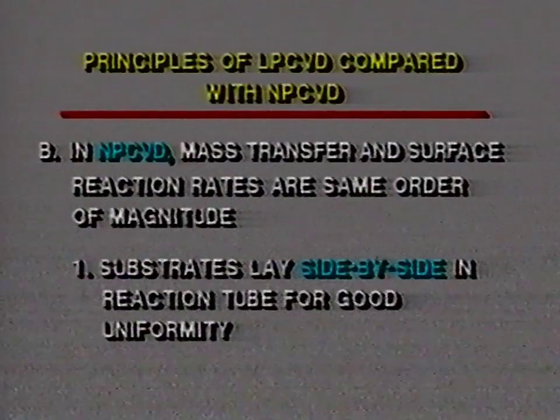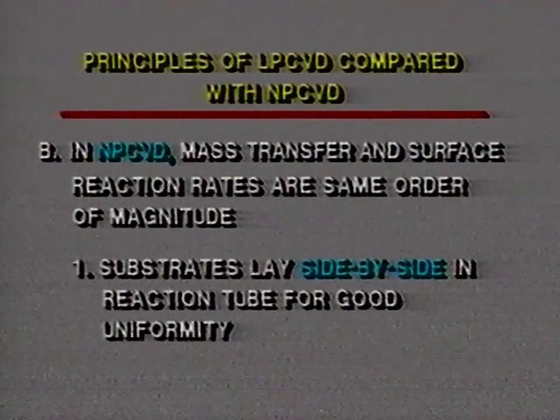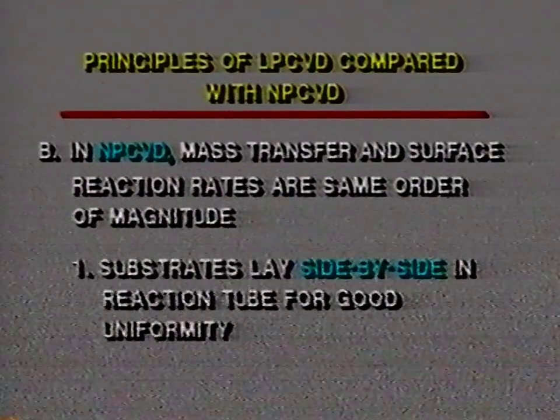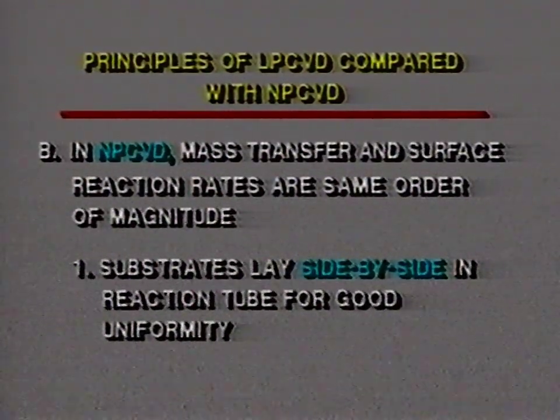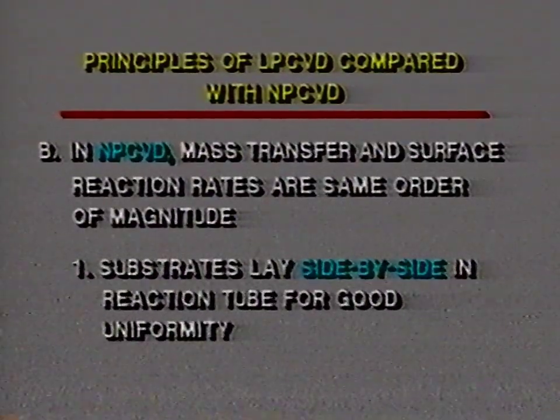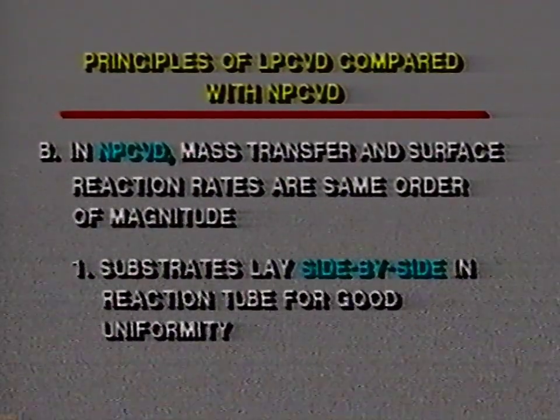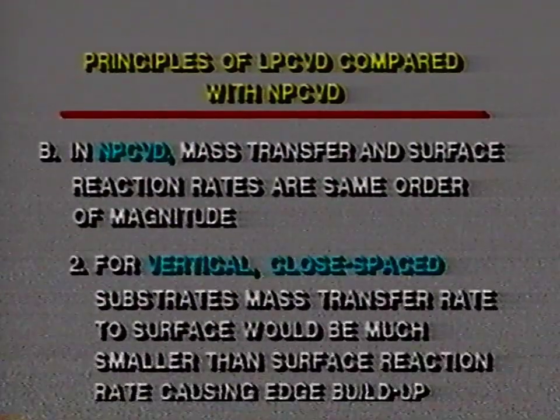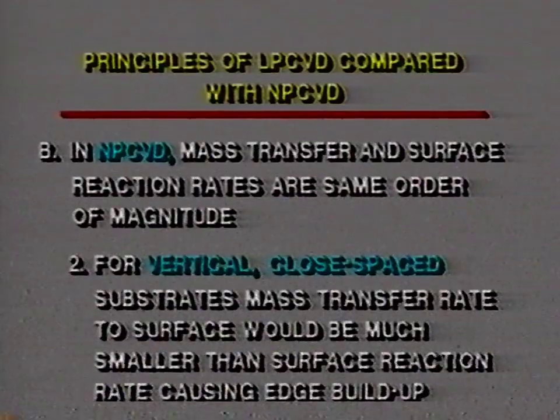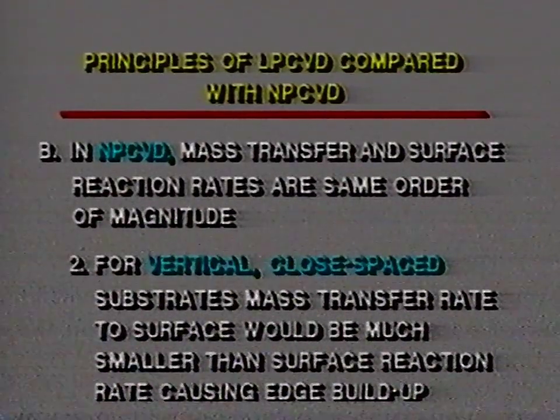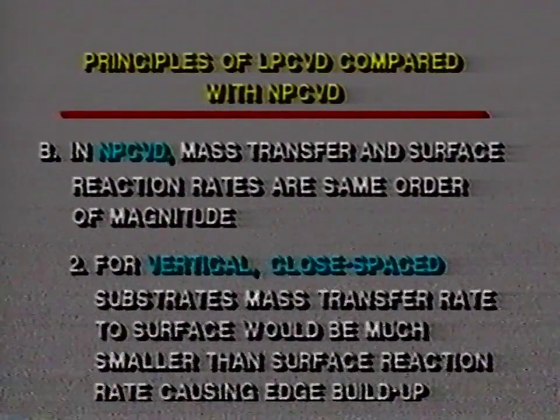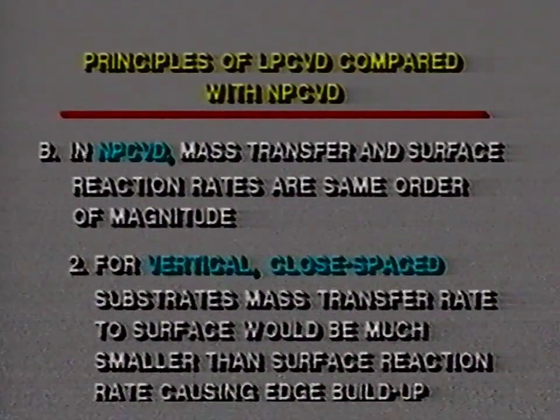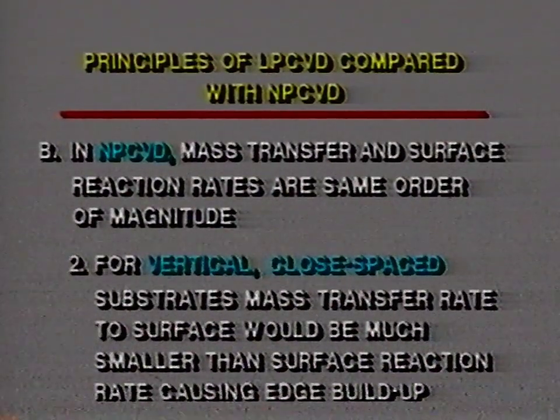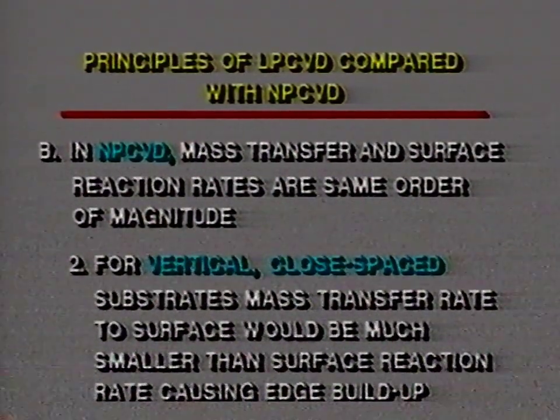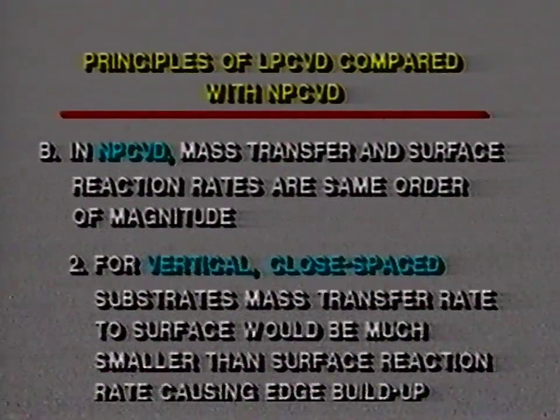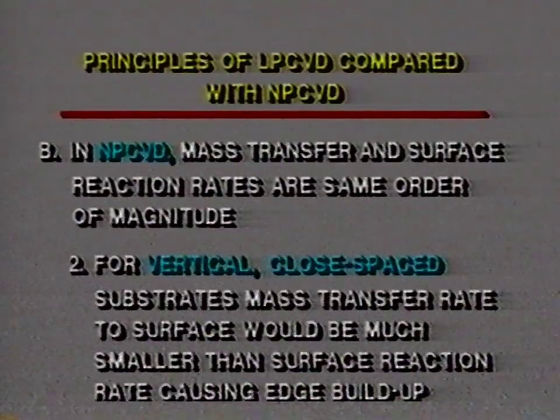Now, if the substrates lay side by side in a reaction tube for good uniformity, as it used to be done before the LPCVD type of processing was developed, it is necessary, in order to get good uniformity, to lay the substrates side by side flat in the tube. If we would stand them up, as we now do in LPCVD, but would use normal pressure CVD, for vertical close-spaced substrates, the mass transfer rate to the surface would be very much smaller than the surface reaction rate and cause, as a result, an edge buildup. In other words, we could not operate at atmospheric pressure with vertical close-spaced substrate wafers.